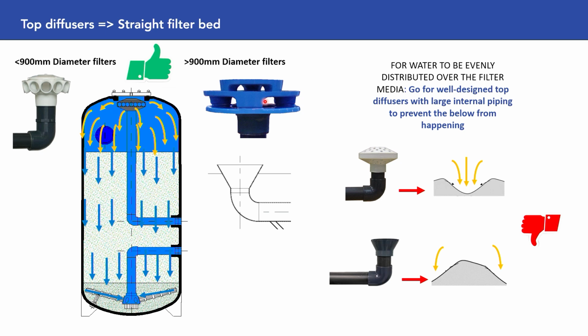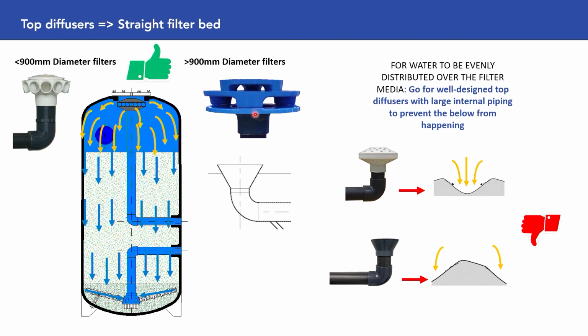The surface of the media is flat, so we don't have a hole or a crater, and this means that the water will go evenly through all the filter media. If we don't have this, for example, with anthracite or sand on top of the media, if we have a hole, we will not have the active carbon in the middle. So the water will go directly to the sand or the AFM, which is not a very good idea and is not what we want. So what is responsible for a flat filter bed is really the top diffuser. You also checked other diffusers, like the Koenig, which are great for backwashing, but they give turbulence where you get these mountains, and other ones which give this hole. The ones that you're using guarantee a super flat filter bed.